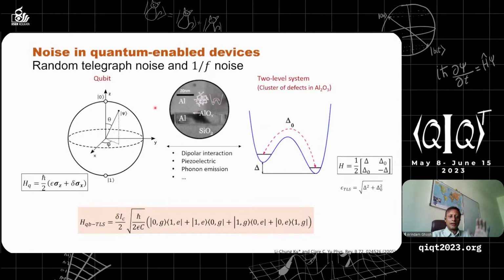So suppose you have something like a Bloch sphere of a qubit made with an aluminum oxide, aluminum junction, and suppose it couples to one two-level system. A two-level system could be a cluster of atoms in the aluminum oxide, for example. And these clusters of atoms are not stable because aluminum oxide is not ideal. It's an amorphous region. And that cluster of atoms moves between two positions. And every time it goes from one position to the other, it can either emit phonons or couple to the state vector through some piezoelectric or dipole interaction. And you can form a Hamiltonian of the coupled Bloch sphere and the two-level system.